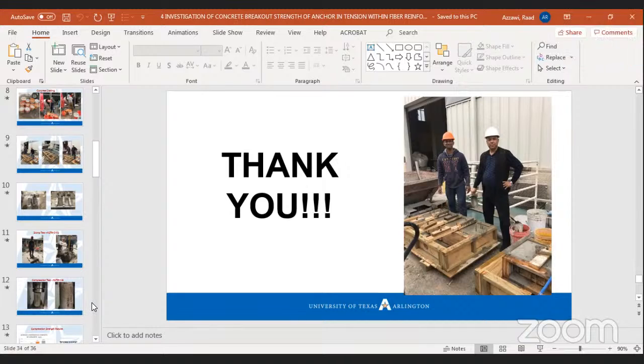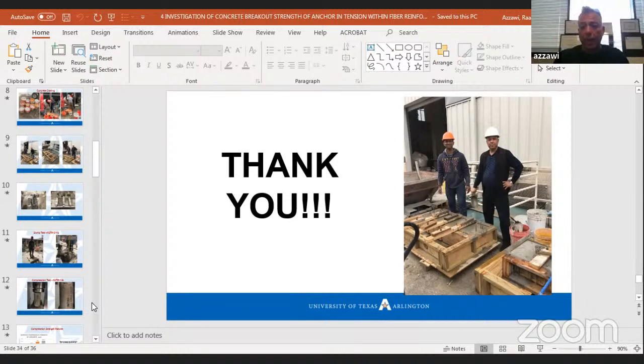Yes, it's good. The results are very promising. In fact, I did it by myself, and I watched it with my colleague. If we need to increase the tensile strength of anchor bolts, any type of anchor bolts, we just need to provide some portion of steel fiber, mixed just in the pedestal, not for the foundation or everything. Just the pedestal, maybe 4 or 5 feet in height. And we will see how much the strength increases. We don't need to use long bars or large-diameter anchor bolts. With reasonable anchor bolts and some portion of steel fibers, the tensile breakout of the anchor bolts increases a lot. This was done experimentally, and I approve it.